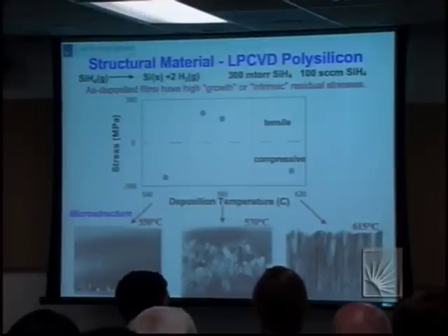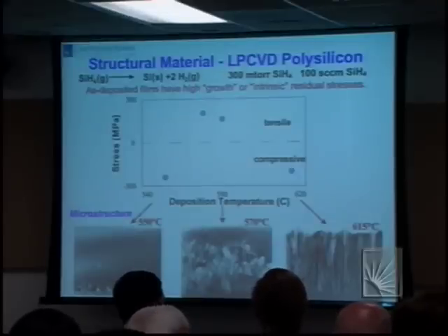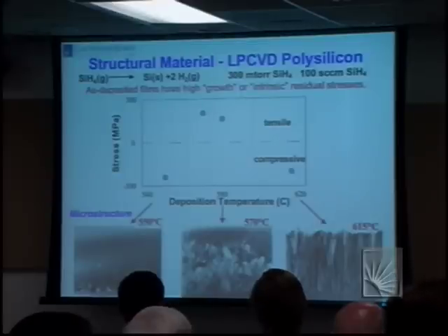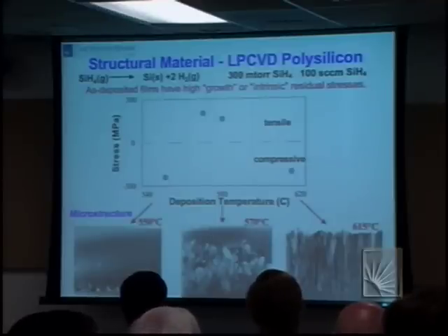And our CVD reactor works in this temperature range of 540 to 620. You can pick any temperature you like in that range, but not much else outside it. The reaction we use is just the cracking of silane under these conditions. And it's inevitable and well known that films deposited under these conditions come down with residual stresses. These are growth or intrinsic stresses, since there's not any real thermal expansion mismatch stress.